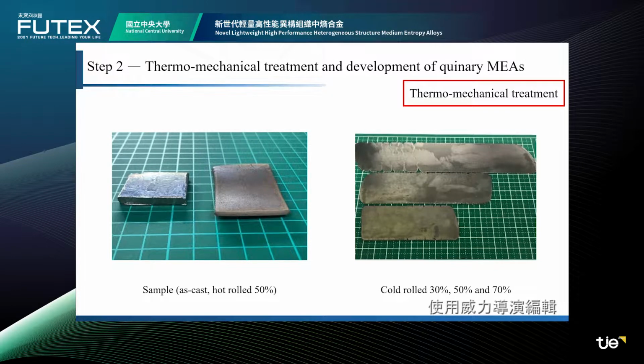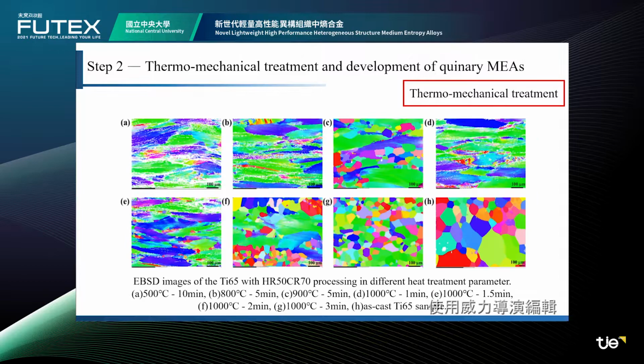Later, based on titanium 65, we introduced thermomechanical treatment in processing. The mechanical properties can be further exploited through different amounts of rolling processing and heat treatment parameters. In the EBSD image, when the annealing temperature is 500 to 600 degrees Celsius, the alloy cannot be recrystallized effectively because the energy is not enough. So a large number of deformation bands will still be retained in the alloy.